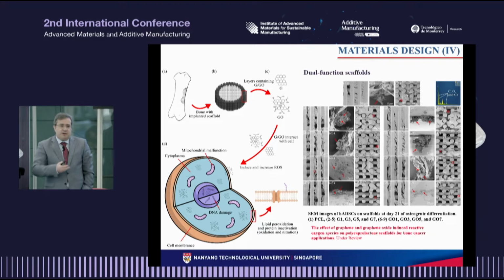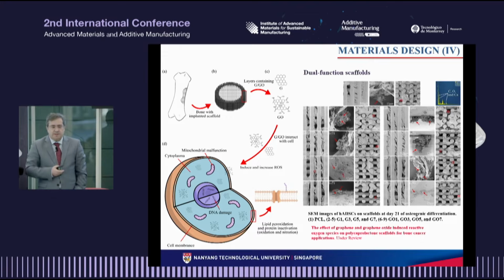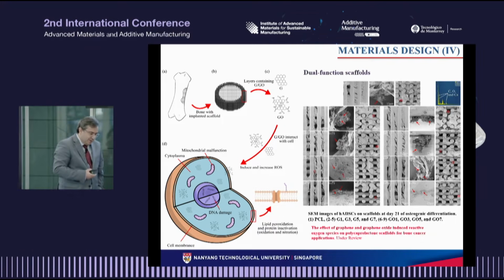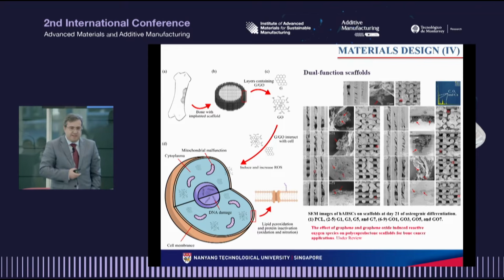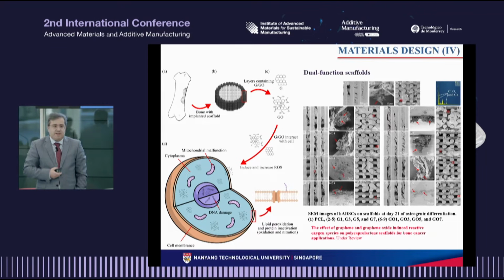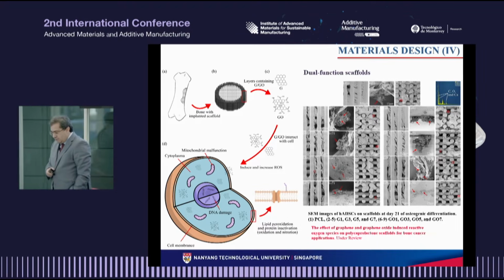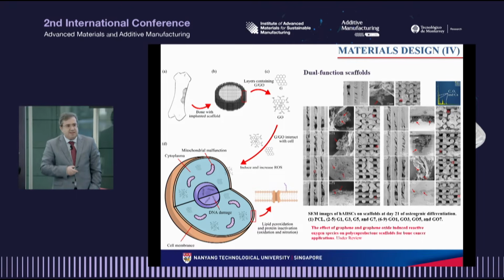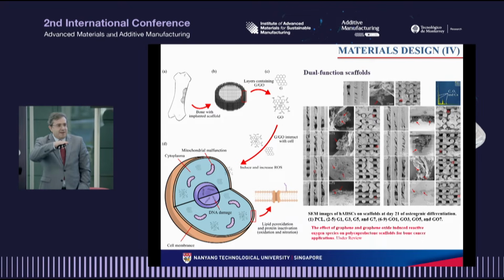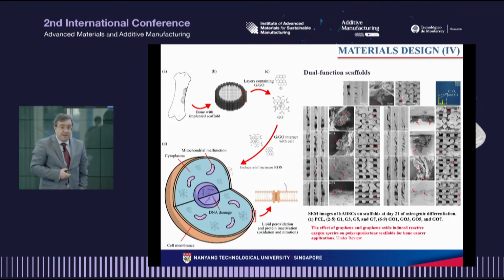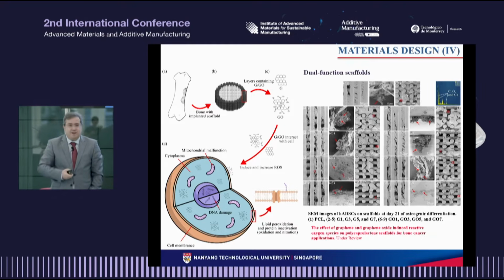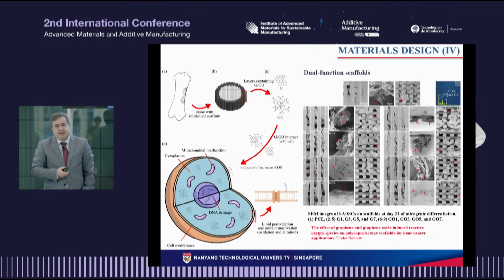So the outer layers of our scaffold were designed to contain very critical levels of graphene. This promotes high levels of reactive oxygen species, inducing oxidative stress. And we realized that cancer cells are more sensitive to these high levels of reactive oxygen species than healthy cells. So our major task was to identify the critical value of graphene to produce enough reactive oxygen species killing the cancer cells without having any impact on the healthy cells.